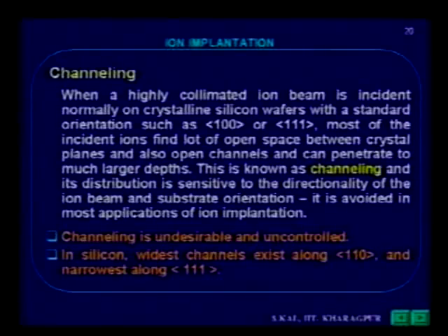Channeling basically is undesirable, as I told you. Why is it undesirable? Because it is uncontrolled. In channeling, since scattering and collisions are less, the stopping mechanism is not exactly estimated by the implantation theories. In silicon, it has been observed that the widest channels exist along the 110 direction and the narrowest along the 111 direction.